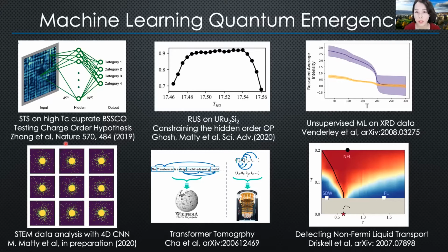Of course, we all see the same thing, and the patterns jump out to us. But when it's human impression, human recognition, it has to go through our brain where other things get mixed in with what we just saw with our eyes. When we used a neural network to analyze the data, we found something very robust over a wide range of doping: a commensurate charge density wave pattern being most dominant, which is consistent with the strong coupling picture of this underdoped data set.